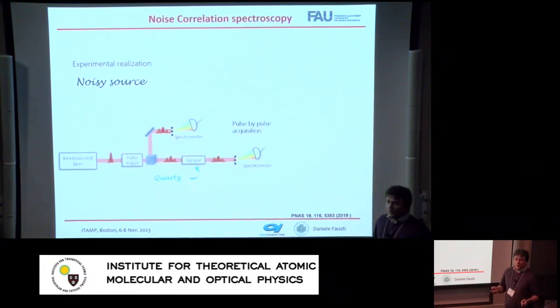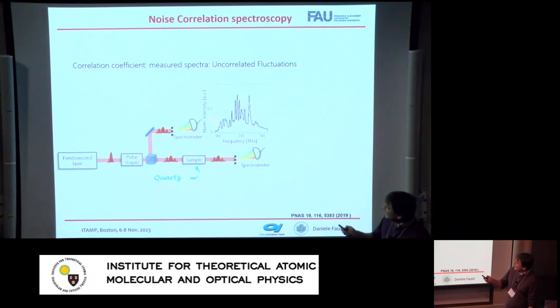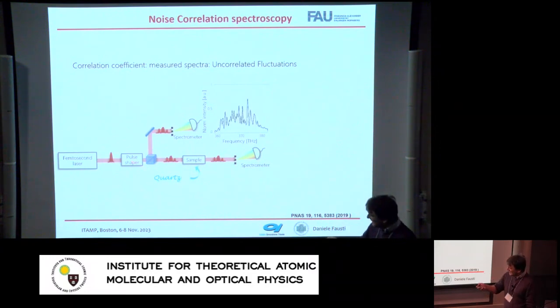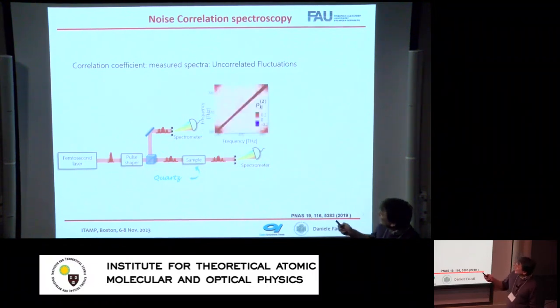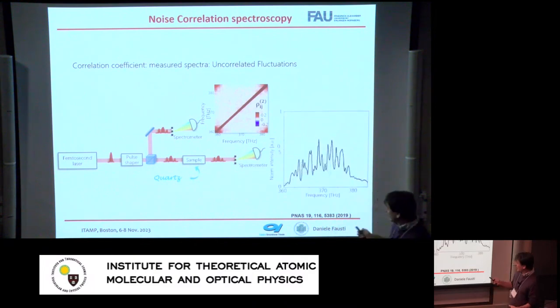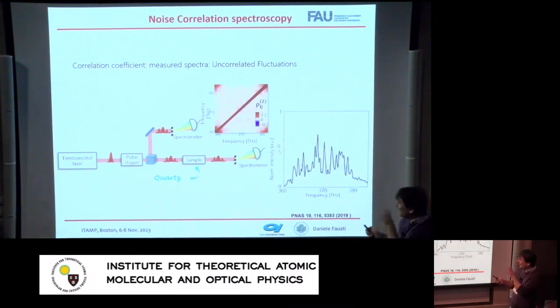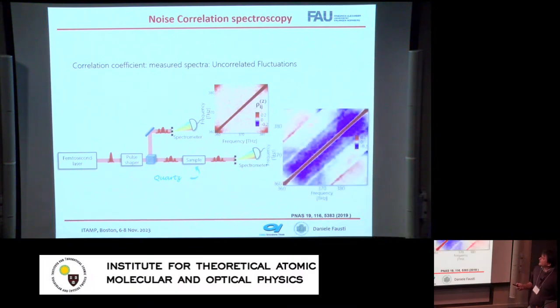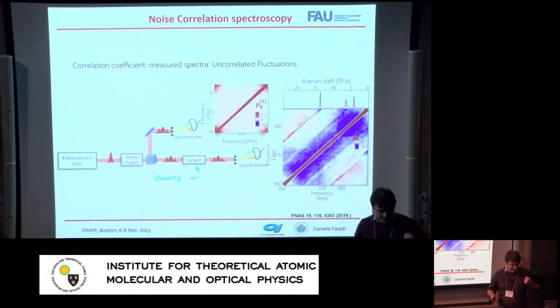This is what we did in the past, and essentially the idea is that we developed means to produce very frequency uncorrelated pulses. This is a measurement of intensity fluctuations in my laser system after I deliberately made it bad. And if I look at the correlation, it is essentially local in frequency. I take the same set of pulses, I make them interact with the sample, and the interaction with the sample may introduce some correlations. Of course, if I look at them pulse by pulse, there is very little I can learn because it's as ugly as before, but if I actually look at the correlations, I see correlations at very specific frequencies, which are the frequency of the phonon which mediated the scattering process. Okay, so the idea is that I try to encode information in the noise and extract information from the noise so that I can sort of cheat around the indetermination.